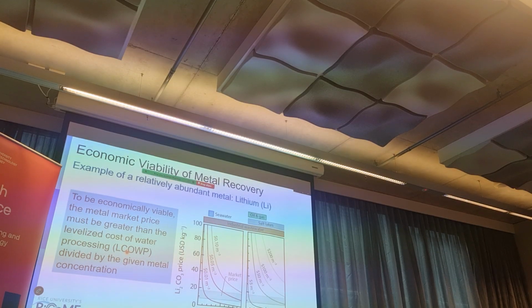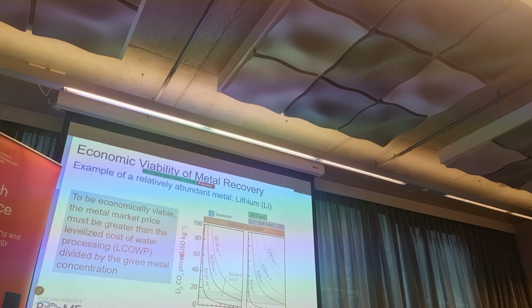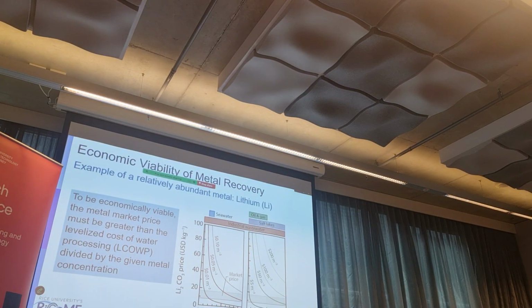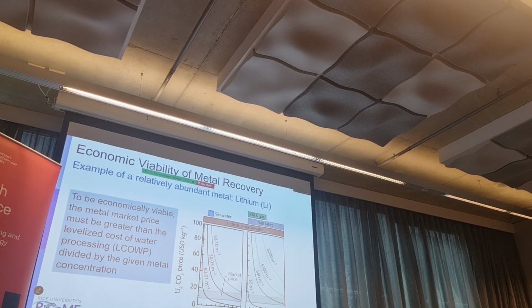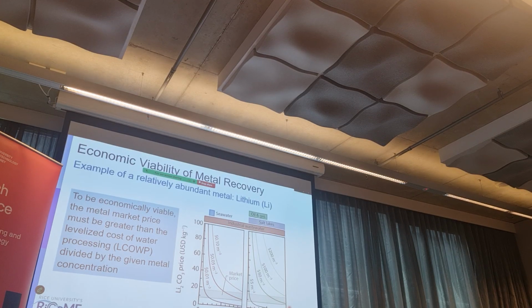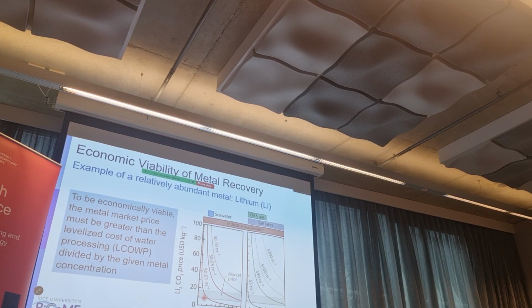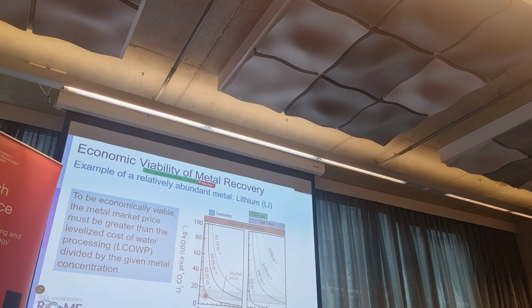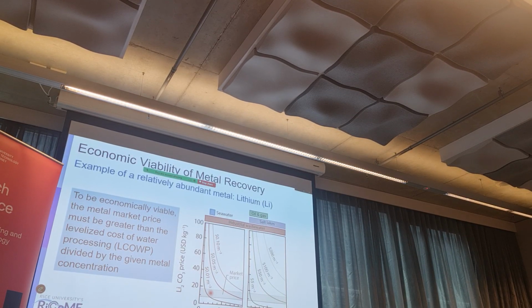We can construct this graph based on this simple equation, presented here for lithium—specifically, lithium carbonate price versus concentration. We have two graphs: concentration up to 1 milligram per liter, and another with higher concentrations. In the shaded area, this is the current price range of lithium when we wrote the article—I think now it's about $10 to $12 US dollars per kilogram.